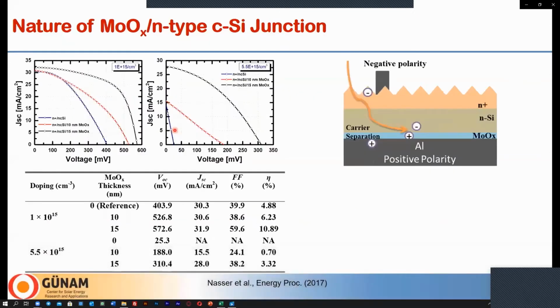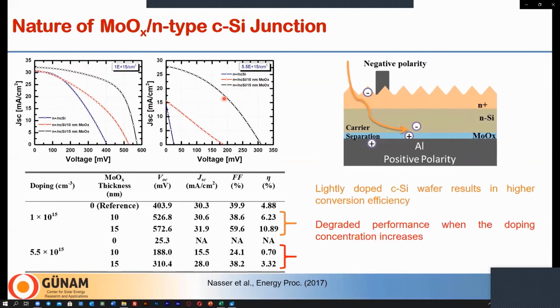And here are the obtained photovoltaic characteristics from the molybdenum oxide back junction solar cell. This one is with the lightly doped wafer, and this is with relatively higher doping concentration. The solar cell with the lightly doped wafer resulted in higher conversion efficiency, while the cell with the higher doped wafer resulted in degraded PV performance.